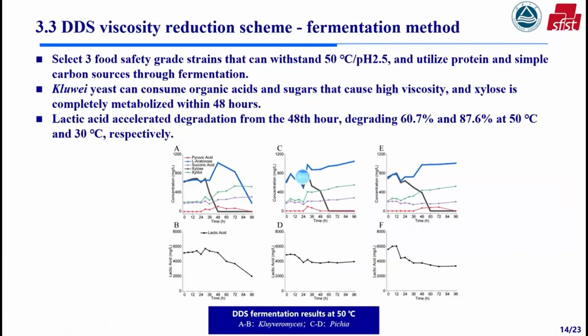In order to further improve the property of DDS, we selected 3 yeast strains for fermentation, among which Kluyveromyces exhibited the best performance. It can efficiently use xylose and lactic acid, and all xylose was completely degraded after 48 hours of fermentation. Kluyveromyces can tolerate fermentation conditions at 50 degrees, which further reduces the cost of microbial contamination and fermentation.